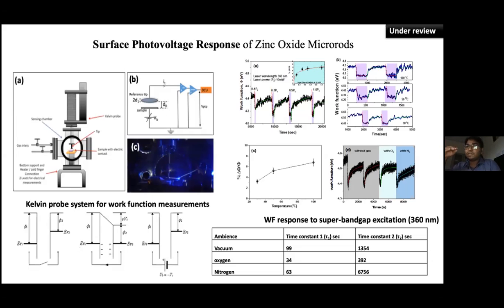So the oxygen which is present on the surface can take up some of these photo generated electrons, basically trap these electrons and reduce your current. So the recovery can be influenced by your surface states. So what we have done is we have looked at the response in work function for different oxygen partial pressures. You can see one is in the ambient condition, one is in full oxygen, and the other is in complete nitrogen. You can clearly see that the recovery varies like this.